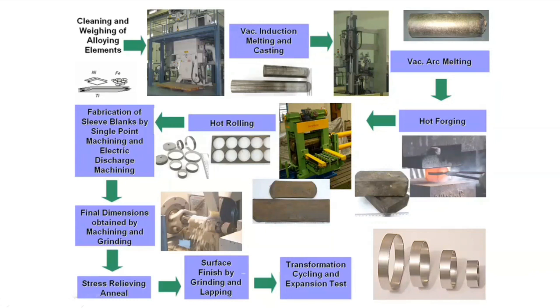It turns out there is a DRX window, a dynamic recrystallization window in that. This was work which Dr. Ashok and we did at IISc, and I think it's Professor Prasad. That was his final work also. Thereafter, he moved away from IISc, and we could do the deformation process maps for this. And you see a window in which you can actually hammer forge. I was very uncomfortable in the beginning because with hammer forging, you hammer it, and my heart was always in my mouth. That's what the material is. But it turns out that is the only temperature, only condition under which you can actually deform it. In fact, if you press forge, it'll fail.